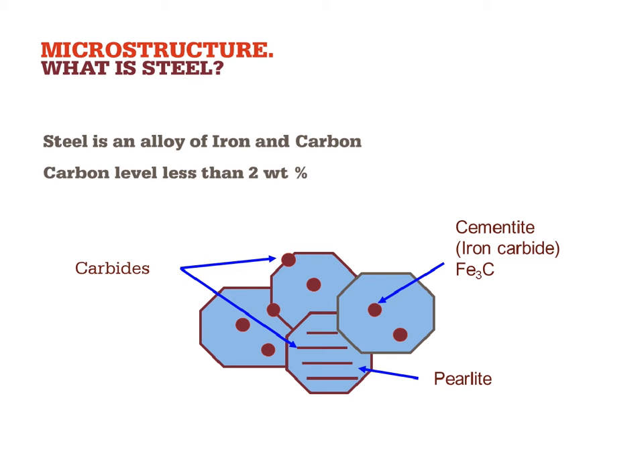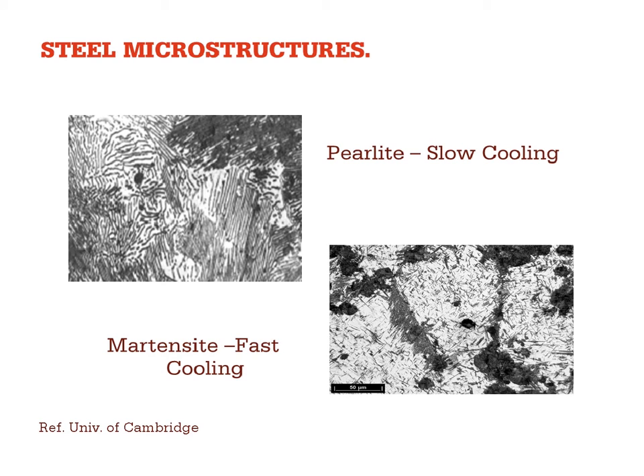This is a schematic illustration of the stripy pearlite structure that I mentioned, but also there can be a tendency for freestanding carbide particulates to form, and those will also contribute to the mechanical properties of the material. So we need to understand all of that. We also have to understand the consequence of varying the cooling rate. So if we take a material up to the austenite region, which if you remember on the phase diagram would typically be around about 950 degrees C, if we cool it slowly, we get the pearlite structure. If we cool it very quickly from 950, we actually get something very different.